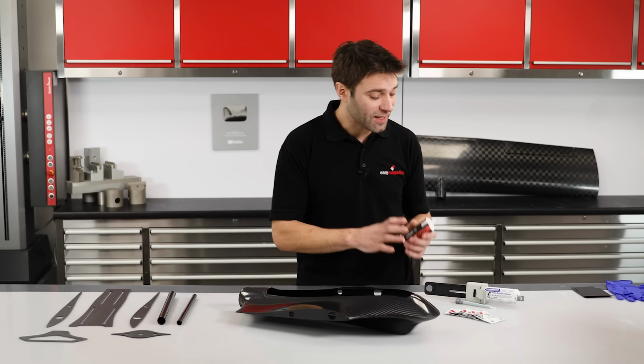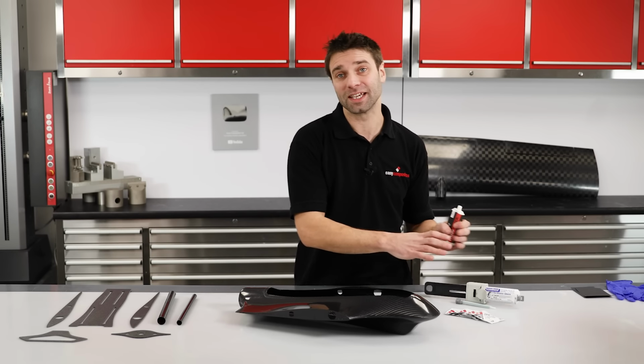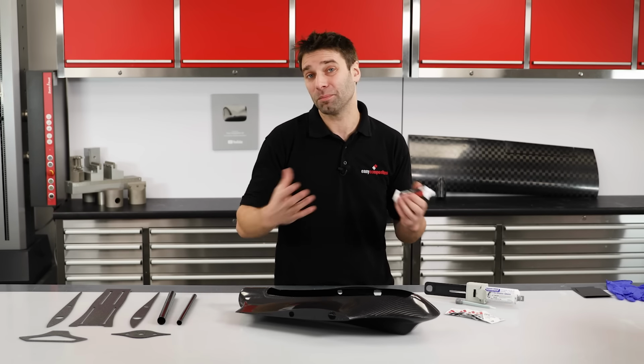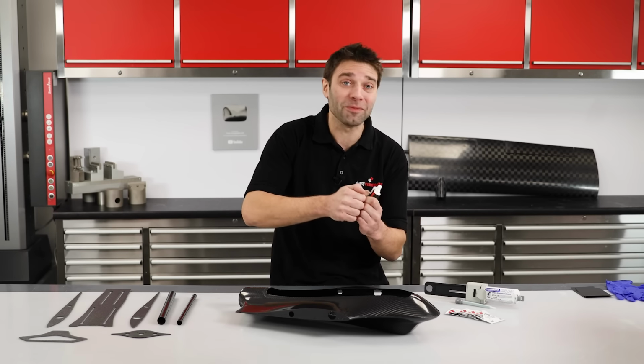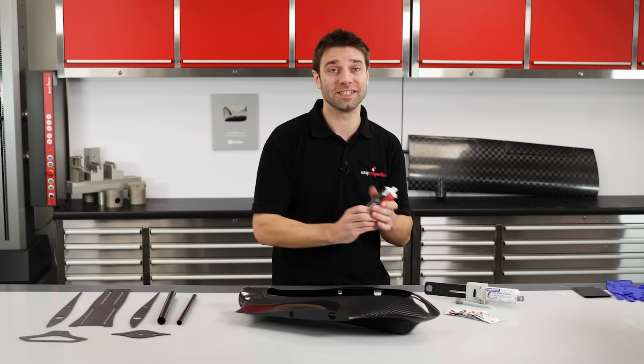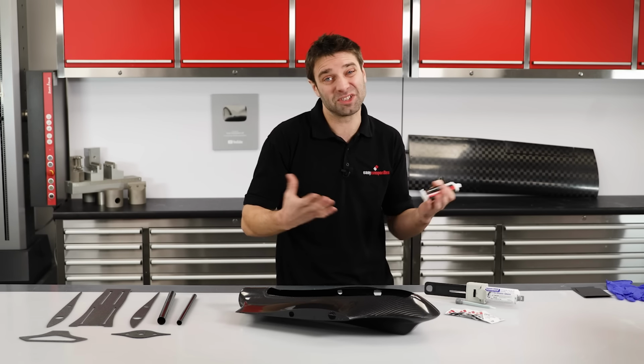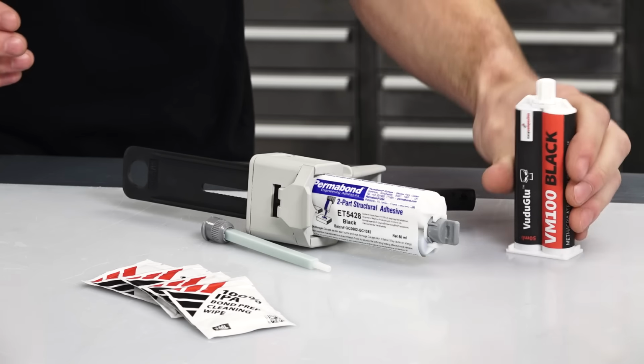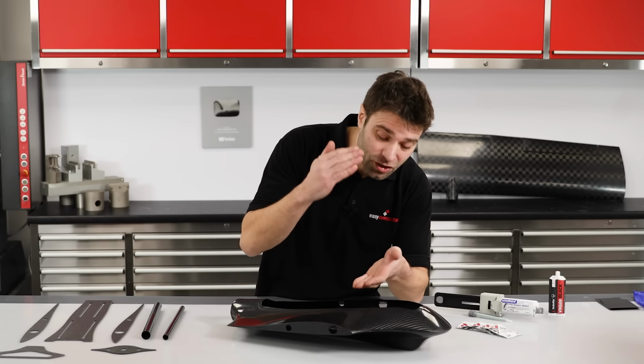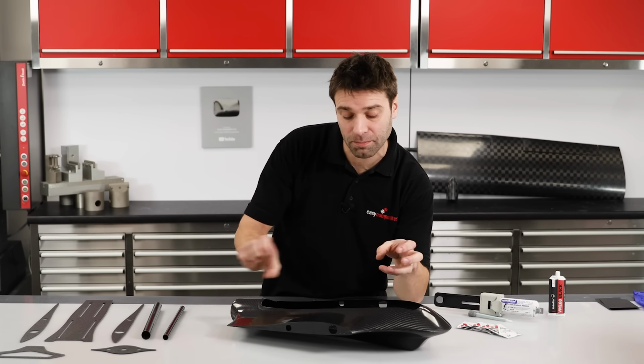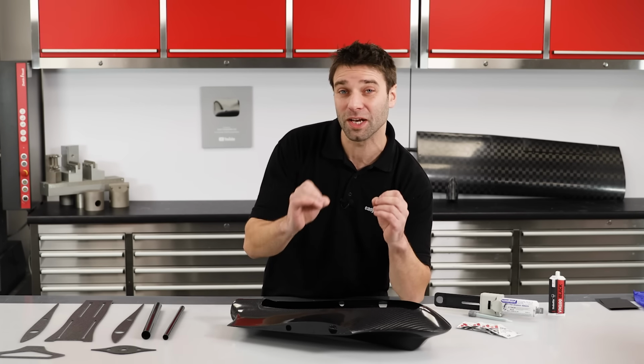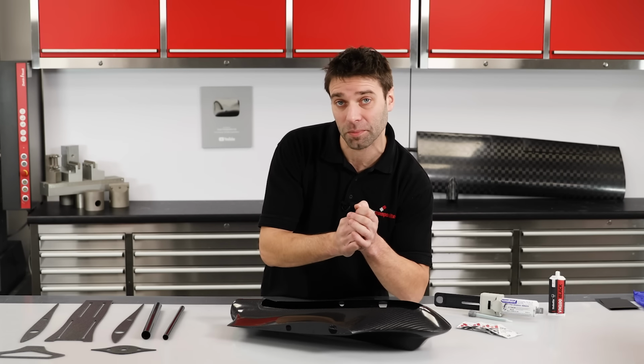And while they don't have the out-and-out performance of an epoxy, generally they will still outperform the substrate. So it's going to be the carbon fibre that tears apart before the adhesive fails. So having a higher performance is pretty much meaningless. But for this application, where we've got really critical edge bonds of these components into the fuselage, we really want the highest possible performance from our adhesive.